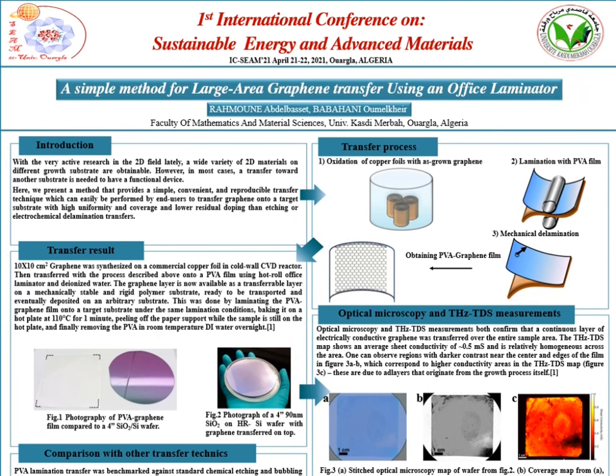Here we present a method for transferring large area graphene using commercially available prefabricated polyvinyl alcohol foils used for hydrographics printing, a commercial tabletop hot roll office laminator, and water. PVA lamination transfer of graphene was performed according to the procedure illustrated in this figure.